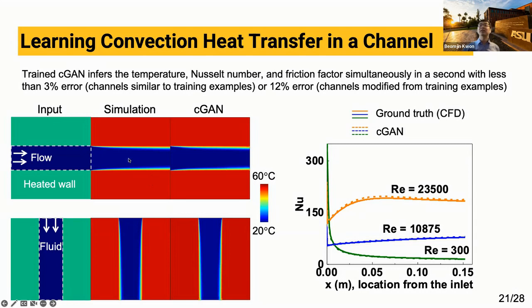So here I show a very simple example. There's a water flow in the middle, which is surrounded by heated wall outside. And the generator network was able to predict the temperature distribution, which is very close to the numerical simulation. And at the same time, it also predicts the Nusselt number and friction factor distribution, which is shown on the right side plot. And this single model can predict for laminar flow, transitional flow, and even for turbulent flow very accurately.